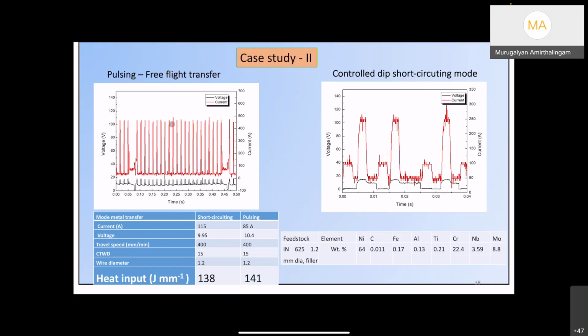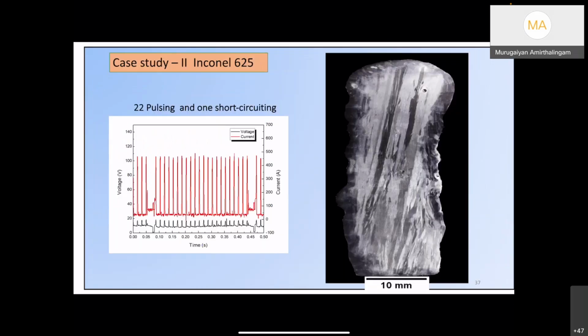So again, one case they show compares this waveform where we have continuous pulsing and the combination of 22 pulses and one short circuiting transfer, and a complete short circuiting transfer, and how the microstructure is going to evolve. So we can also manipulate the current voltage waveforms, as we have over here, so that we can get a completely directionally solidified microstructure, what you see over here. And this is beneficial because a coarse grained directionally solidified microstructure is widely preferred for creep applications and high temperature applications, because it serves better. If the grain boundary area is reduced, it's better for high temperature properties.